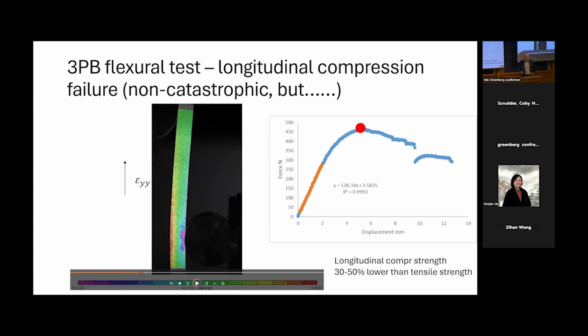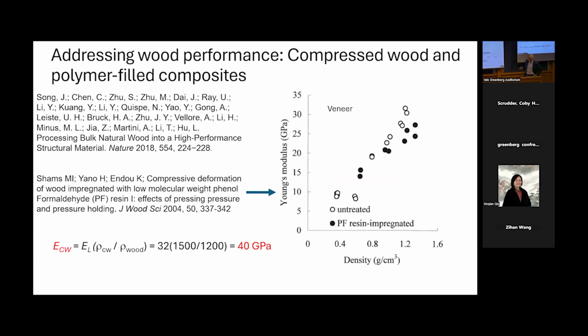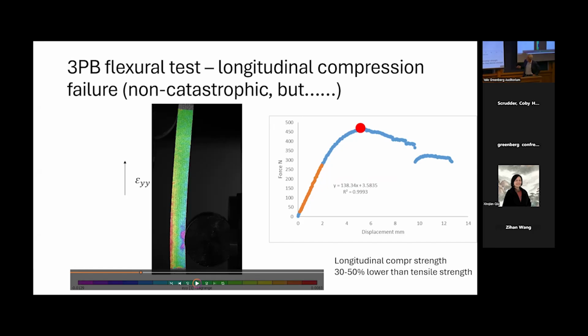I also wanted to point out that it's not only about tensile properties. Many times we load structures in bending. This is the point at which the load is applied. As you can see, there are substantial local strains, and that's because the beam fails in compression, because the compression strength is much lower. So the compressed wood that Bing is working on is very favorable in this respect. You can address this problem. Also, if you add polymer matrices, you can address this.